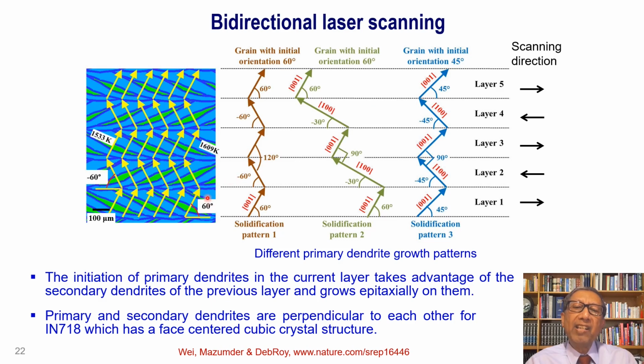If the primary dendrites grew along the dominant heat flow direction, then this would be the solidification pattern, and the grains in different layers would be aligned to this pattern. But that is not what happens. If the primary dendrites followed the 60-degree pattern with the scanning direction, then it would have followed this solidification path too. But that does not happen.